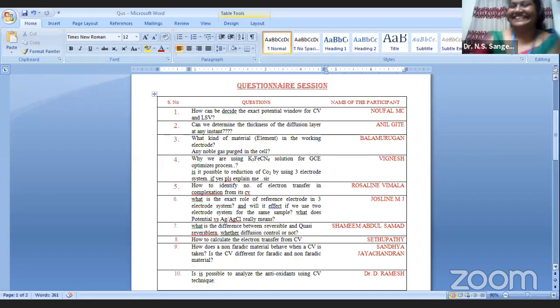Sure. So, how can we decide the exact potential window for CV and LSV? That depends on two things. One is the stability of your electrode material and the stability of your electrolyte solution. If you are using aqueous solution, you should always restrict your potential window within 1 volt, because beyond 1 volt you will be splitting water, and that can happen even at lower potential if the electrode material is highly catalytically active for splitting water. So it actually depends on two things. One is the electrochemical stability of your electrolyte, and the second is the nature of the electrode material that you use.